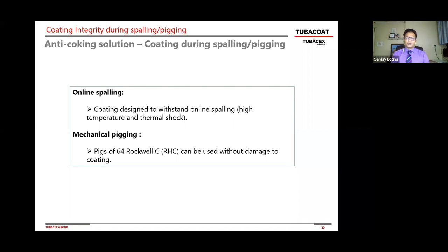And also remember, when we use these coated tubes, we're reducing significant amount of inorganic contaminants, such as the iron sulfide and the solid coke. So the mechanical pigging requirement is significantly lower, but also the material you have in the tube that's coking is significantly lower for the inorganic materials. That's another part. Next slide.